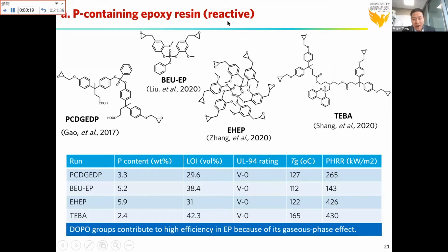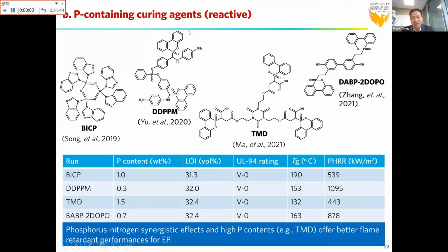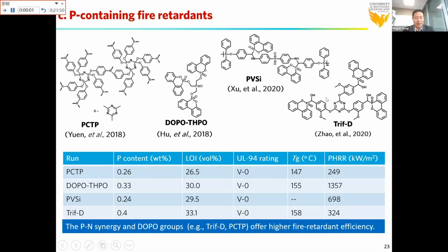You can make a reactive phosphorus-containing epoxy resin, and also phosphorus-containing curing agents for epoxy resin, and also additive phosphorus-containing fire retardants, and you just need a very low phosphorus content. For example, this is 0.24, you can get a V0 and a high LOI. So basically, phosphorus and nitrogen synergy and phosphorus-containing flame retardants are the best choice for epoxy resin.